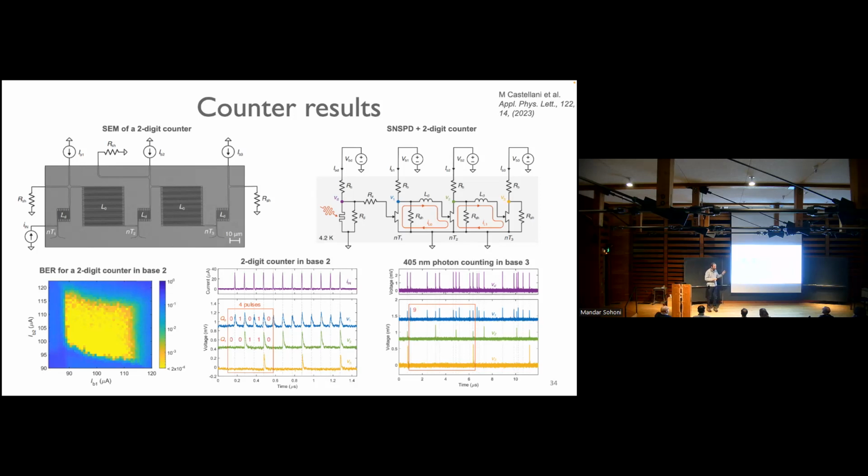In these superconductors, they're very thin. They have a very large magnetic penetration length, much, much longer than their thickness. As a result, they have very few charge carriers. The Cooper pairs famously are the charge carriers for a superconductor. Here we have maybe a few thousand charge carriers per cross-sectional area of the device, micron length. I'm sure that number's wrong, but it's small.